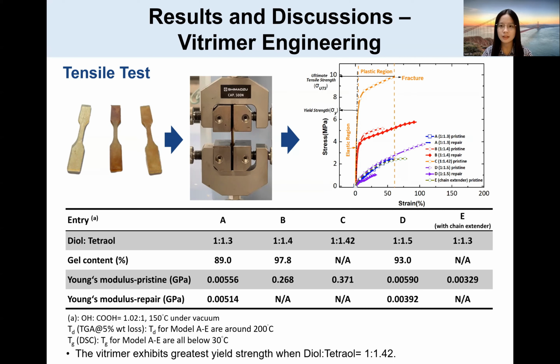And the optimized condition I found is when the ratio of OH groups to carboxyl groups is 1.02 to 1, and the ratio of OH groups from diol to tetraol is 1 to 1.42, as shown in Model C, which is also the same as the orange curve shown here. So by adjusting the formulation design, I found the vitrimer of highest rigidity.